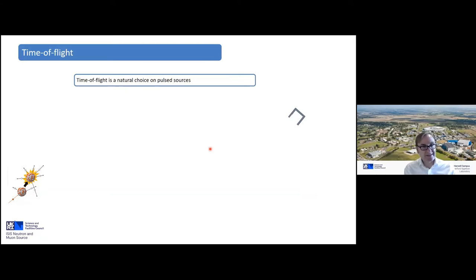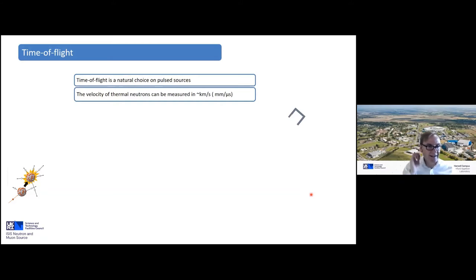So time of flight is a natural choice for pulse sources, because you'll see that by knowing distances and times, you can determine the energy and wavelength of your neutron, and therefore you can do your scattering and elastic measurements and so on. Typically, just as a piece of information, a thermal neutron is of order kilometer per second. So if you can measure distances to better than a millimeter, you need to be timing on the kind of microsecond timescale. And that's all very feasible with modern electronics. I'm very poor at PowerPoint animation, so I'm going to skip that. But that was a proton beam hitting a target, neutrons being produced, moderated, interacting with a sample and going into a detector.